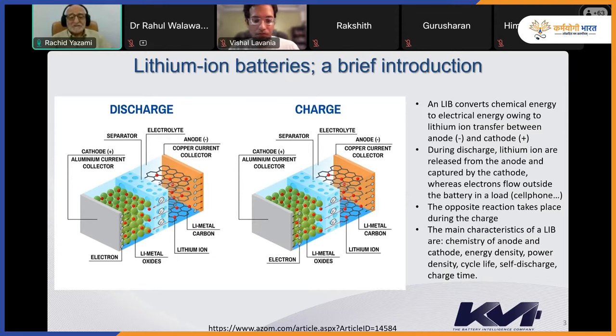Okay, so now the battery is charged. We have taken lithium from the cathode and put it in the anode. During the discharge, the reverse reaction takes place, which means the lithium is deintercalated from the graphite, goes into the electrolyte, diffuses in the electrolyte, and is then captured by the cathode. During the charge, as lithium is deintercalated from the cathode, an electron is emitted. That electron circulates in an external circuit, which is the charger. Then the electron is injected in the anode side, and the combination of lithium ion and electron makes a kind of metallic lithium intercalated between the graphene layers.